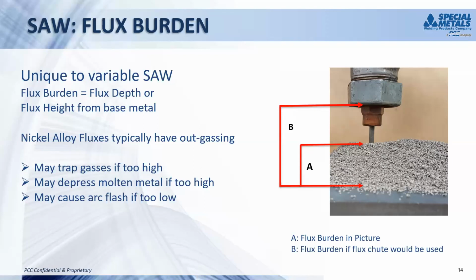This is a very exaggerated picture of a flux burden, but it does clearly illustrate the difference. If you were using a typical flux chute and just dumping it on there, you're going to end up with 3 to 4 inches of flux burden that can really cause some problems in nickel, where on a steel weld, not really as much of an issue.